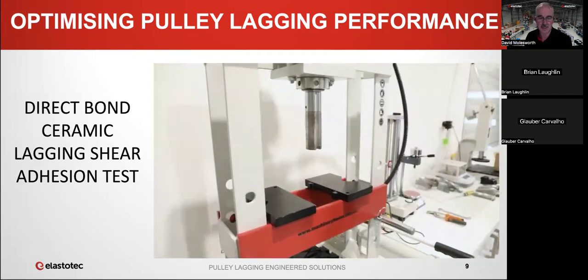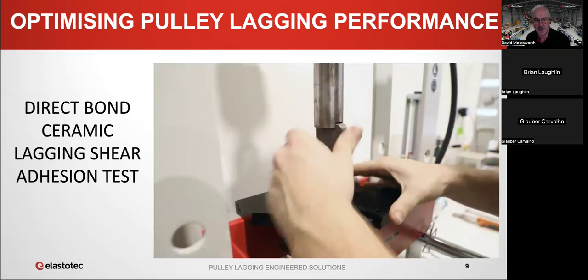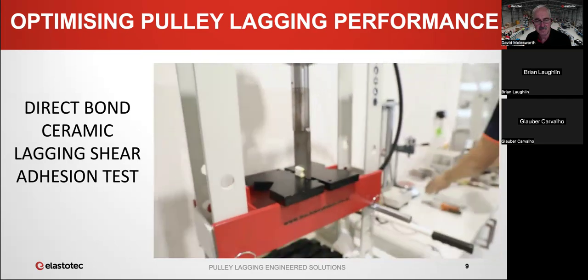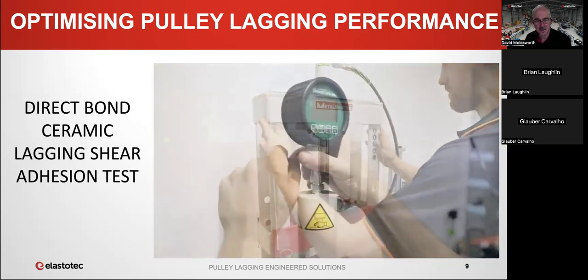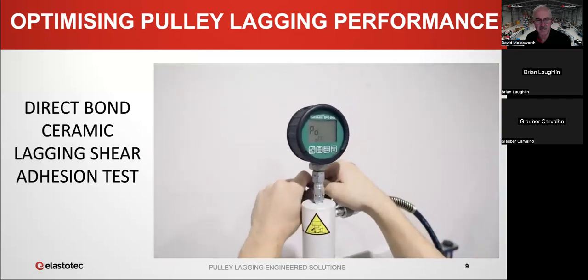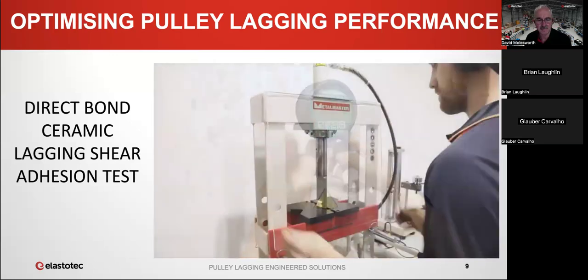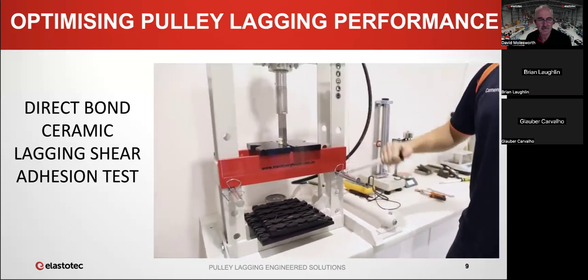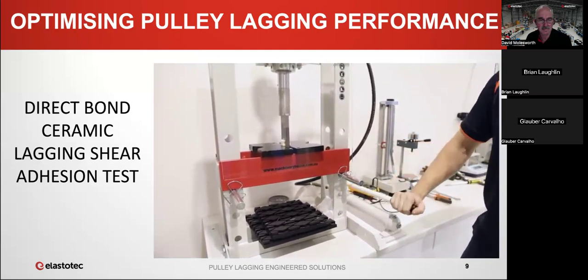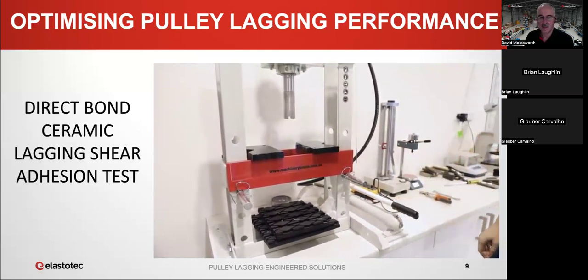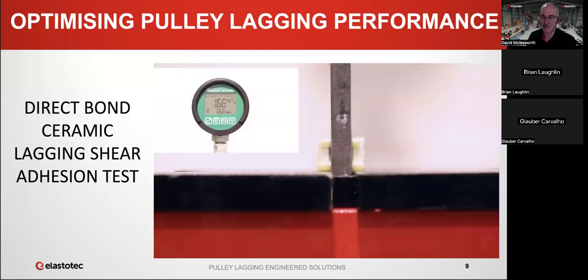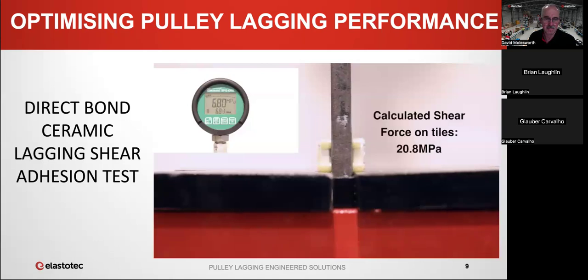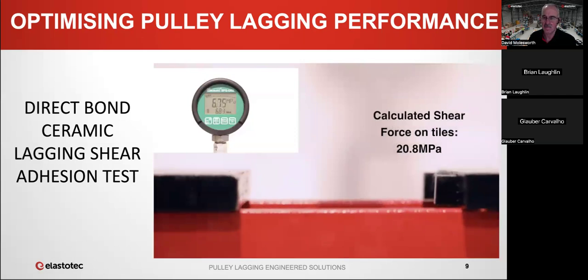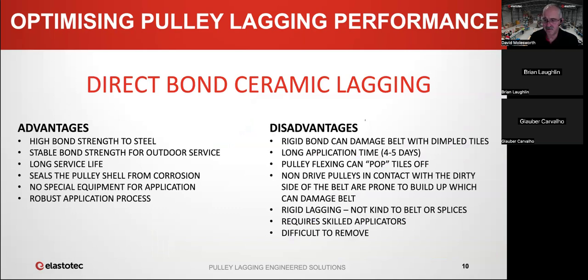This is the test procedure. You see there's a steel sample with a tile bonded on each side. We're going to apply a load to the steel plate and measure the force that it takes to shear the tiles off. Okay, the adhesion force in this test was approximately 20 megapascals. Now the spec that's used in Australia for direct bond is a Rio Tinto spec, and they require a minimum of 15 megapascal shear force.